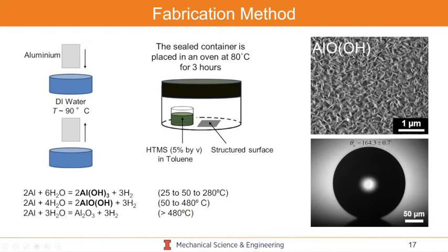When you do it, you're not going to see it, but if you took this and put it in an SEM, you would see flower-like structures on the outside. That's the beauty of this process: it's very simple, very cheap, and very scalable, right? Dipping a large, very complex piece into heated water is quite easy in terms of an industrial process. Afterwards, we do atmospheric chemical vapor deposition to make this surface super hydrophobic, because after you form the aluminum hydroxide, it's not super hydrophobic. You have to add that chemical layer on the outside to make the water like itself more than it wants to wet the surface. You end up with a highly spherical droplet morphology, which is great for droplet jumping.